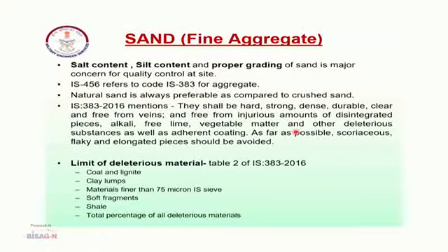In case of fine aggregate, here also we generally take sand from the quarries, and in case of Kanasar there was a quarry from Kolayat where salt content was very high, and if it is not washed properly then it creates a dangerous effect for durability of the building. So, these are the tests which are mentioned in IS 383 which we must do very methodologically.